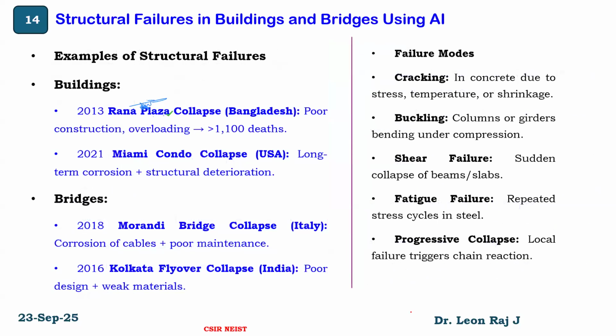Then examples of structural failures. There was the Rana Plaza collapse in Bangladesh, where poor construction and overloading led to more than 1,100 deaths. Then the Miami condo collapse in the USA, which was due to long-term corrosion and structural deterioration. So even though there were multiple mechanisms to monitor the quality of bridges and buildings, this collapse has been seen. Then bridges: the Morandi Bridge in Italy collapsed due to corrosion of cables and poor maintenance. You can see maintenance is a serious issue here.